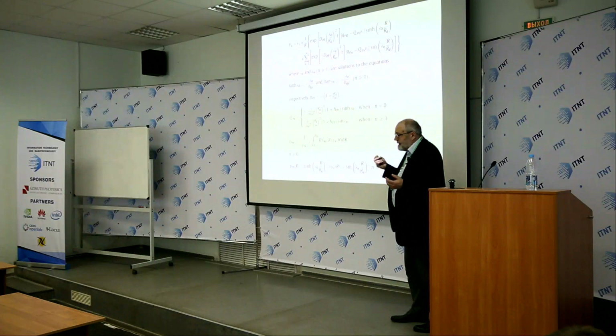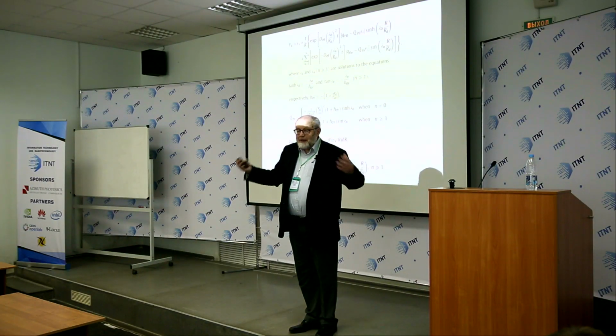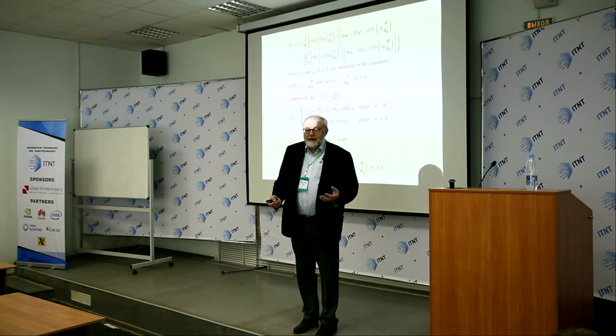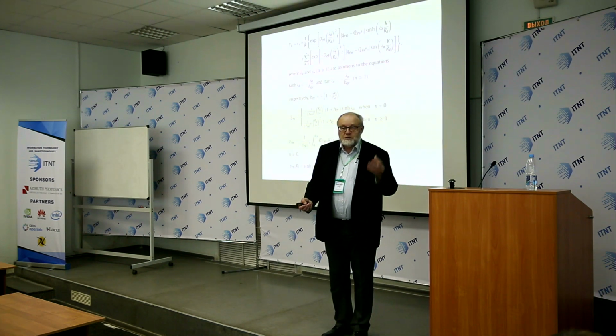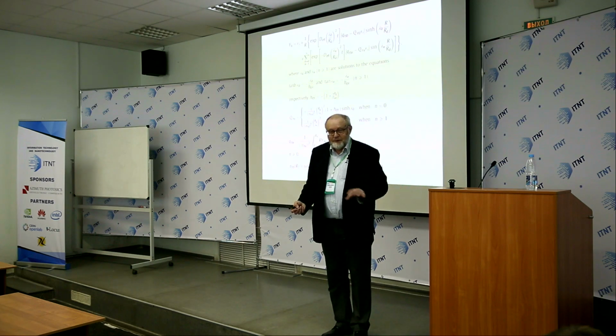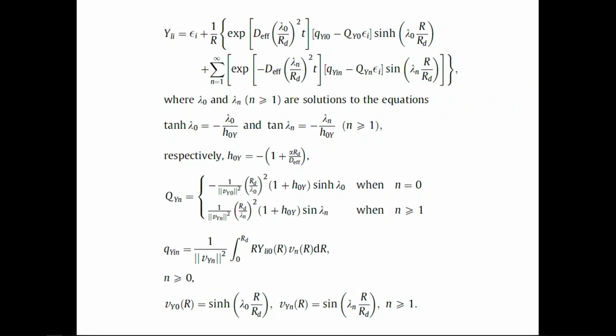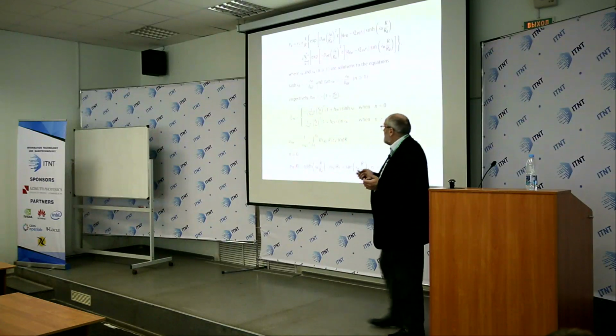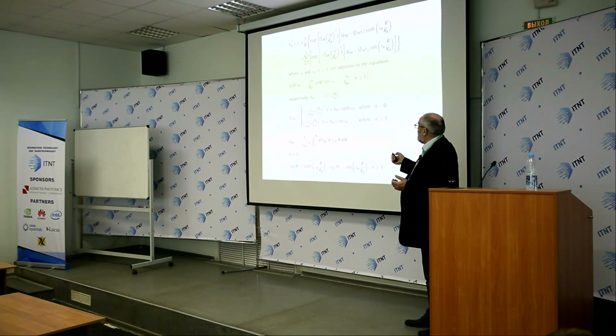And then, once we made this assumption, we are on track with the model which was developed for completely different problems, the model which was developed for automotive fuels. This has nothing to do with automotive fuels. And we use the same equation for species diffusion, which was shown in the background. And then this equation can be solved numerically, and this is something that was done in several papers. But in our case, it was solved analytically. And this is the analytical solution to this equation.